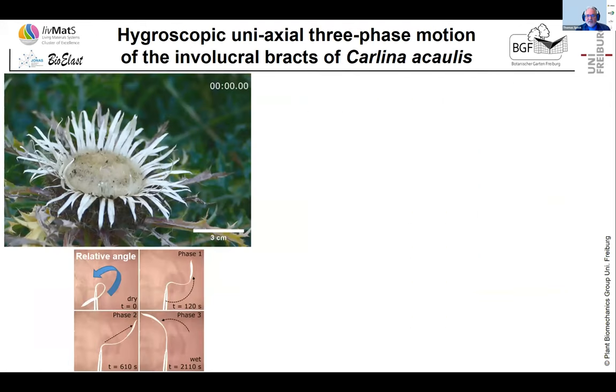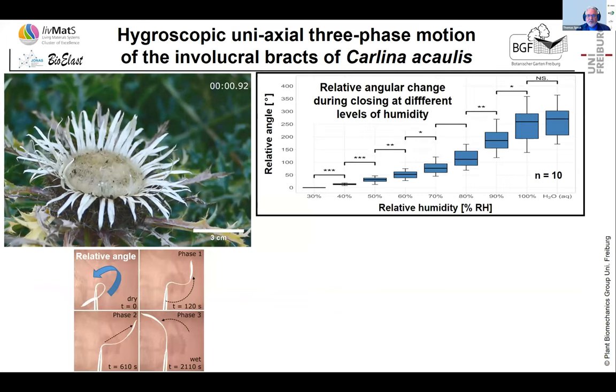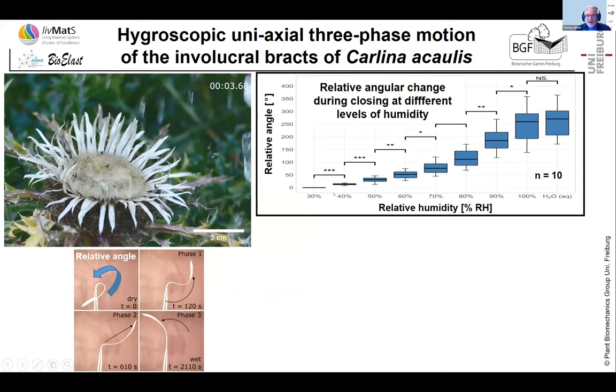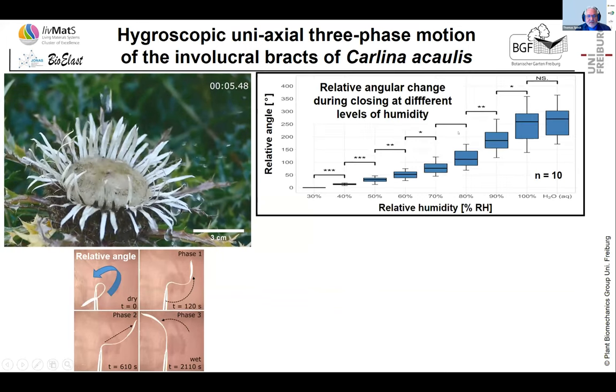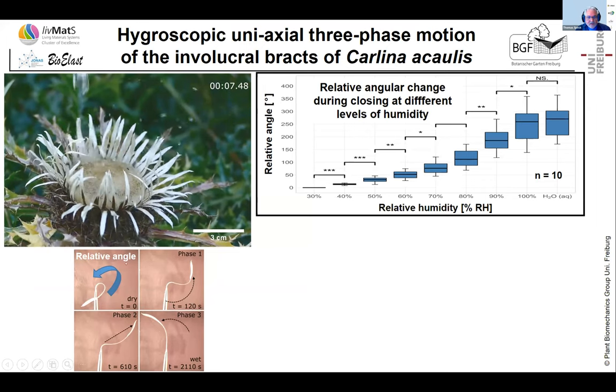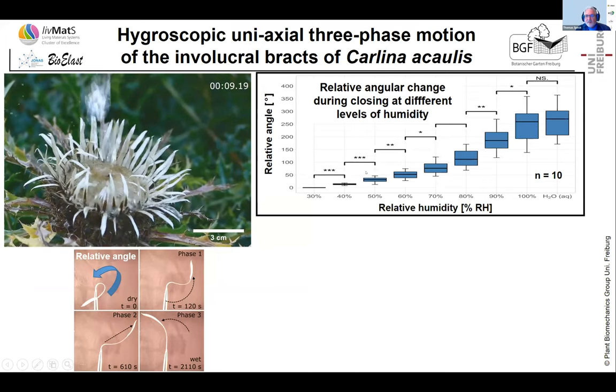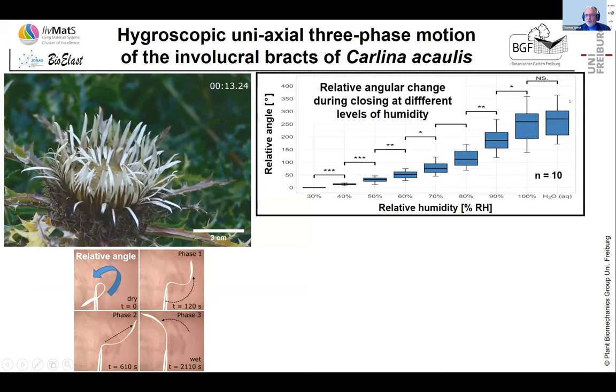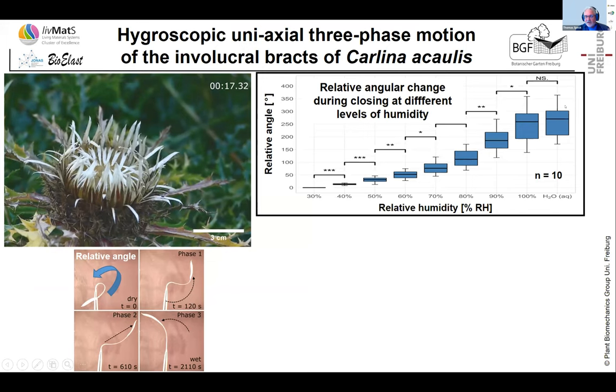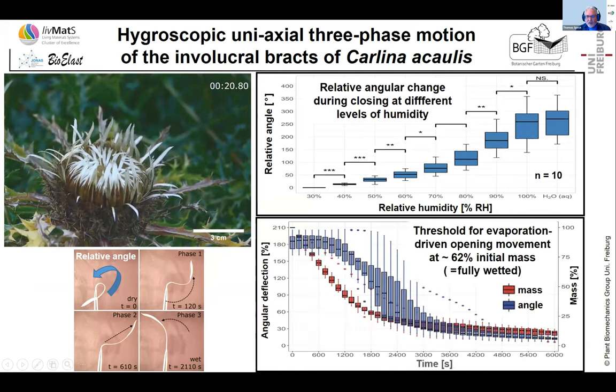So what we did first, we did some analysis, and what we could prove, okay, this is very nice. Here you see how we measured the relative angle of these bracts. This goes more or less linearly with the humidity, which is very nice for a technical application. What's even more important, in my opinion, is that they have a kind of